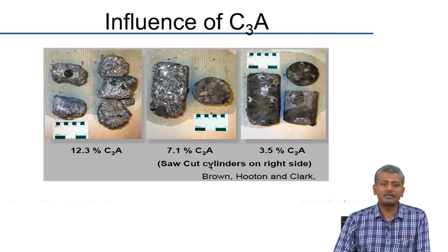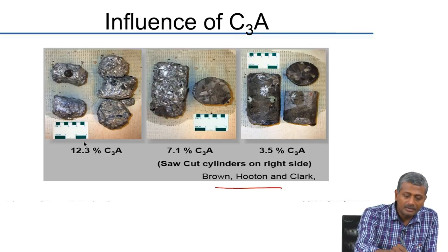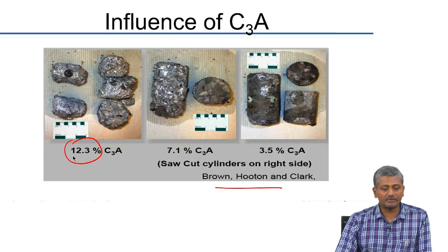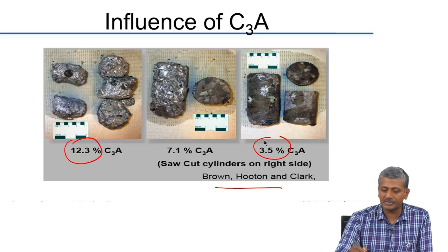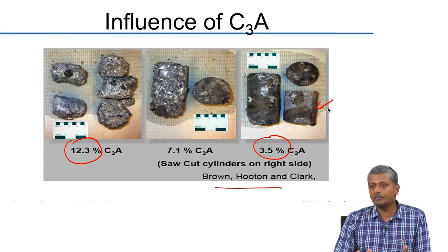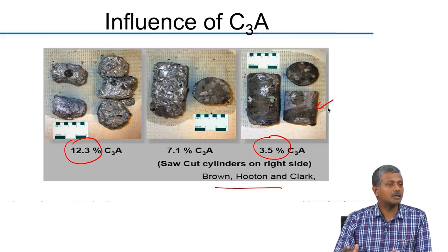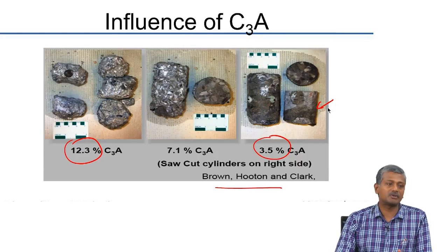Some laboratory evidence about the influence of C3A in sulphate attack, from Canada: if you have 12.3% C3A in your cement, the specimens stored completely immersed in sulphate solutions are barely recognisable, whereas with 3.5% C3A the cylindrical specimens are actually intact after exposure to high-concentration sulphate solutions. C3A level clearly shows the performance of concrete with less C3A to be much superior compared to concrete with higher C3A.